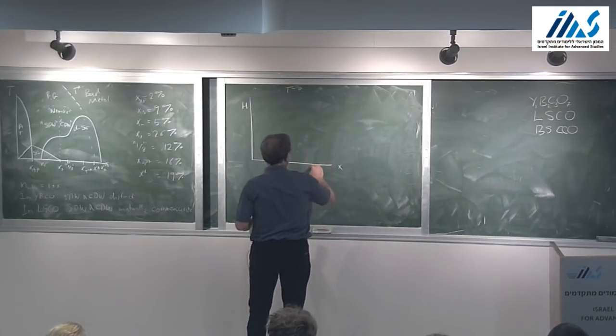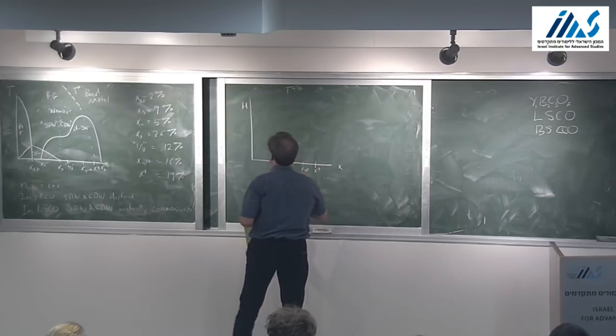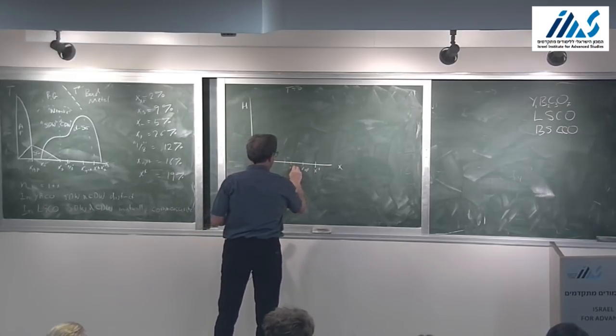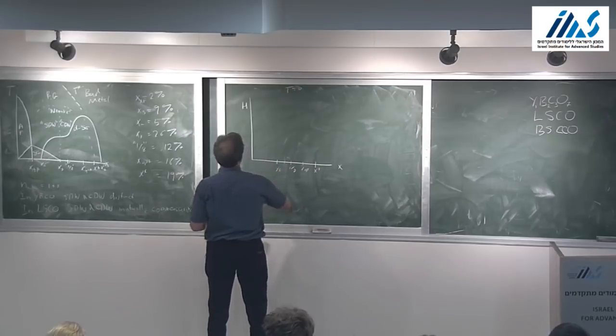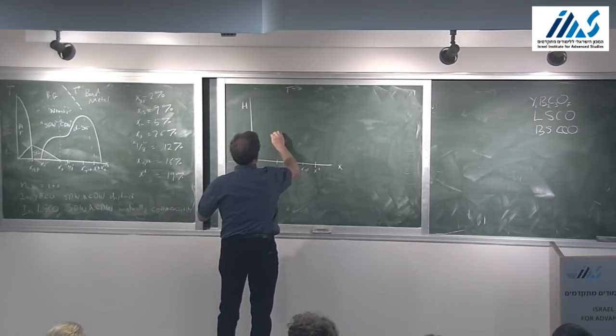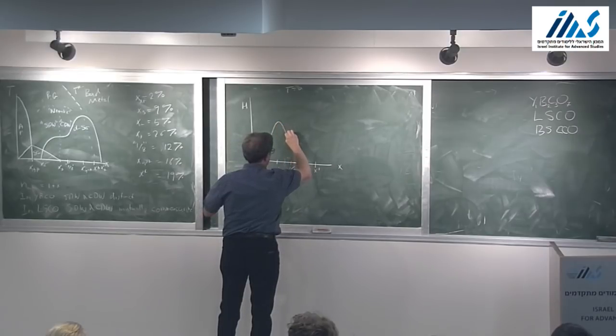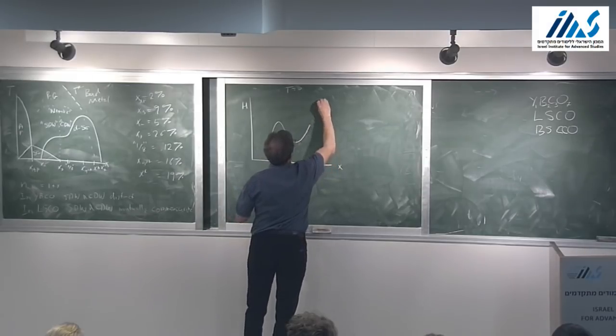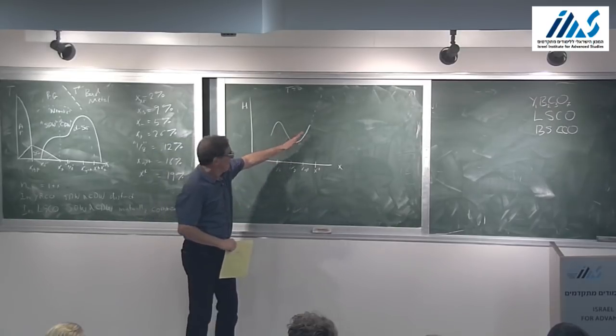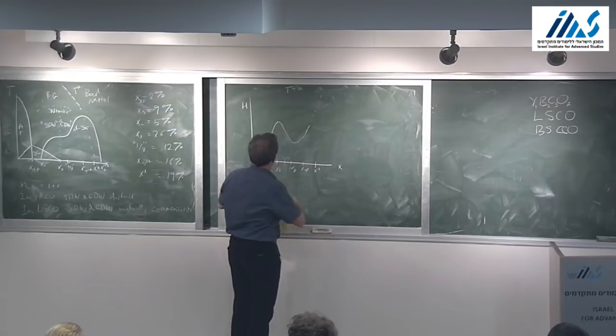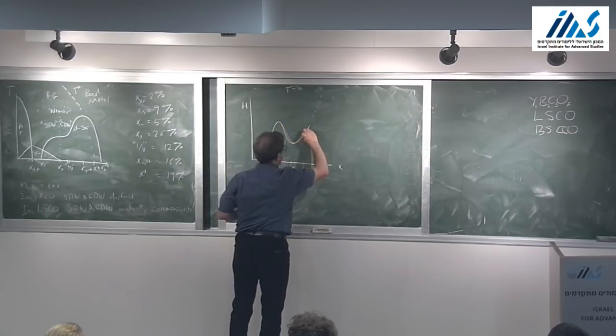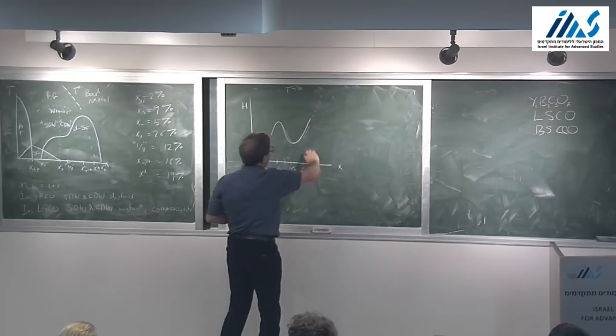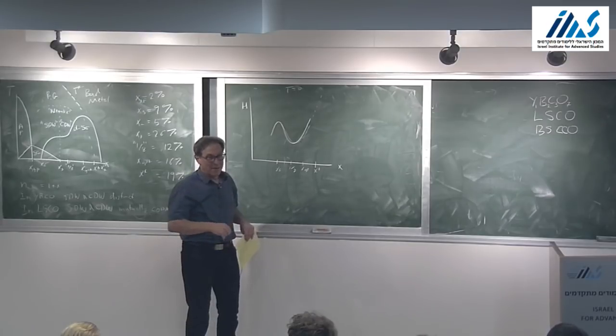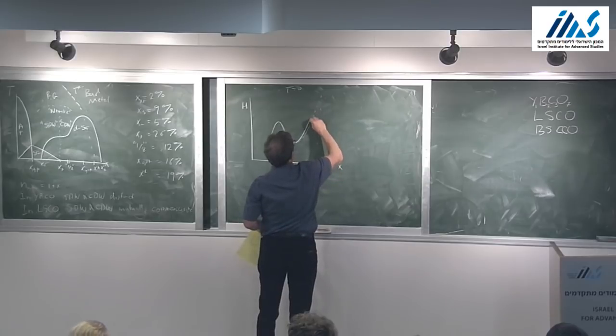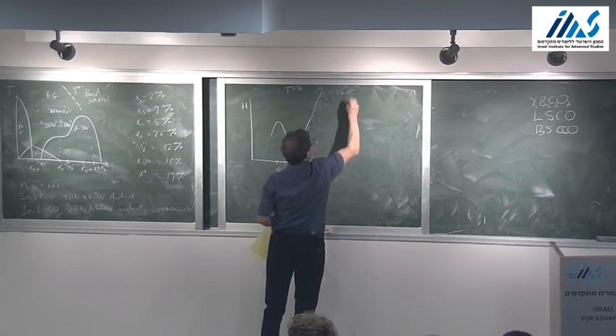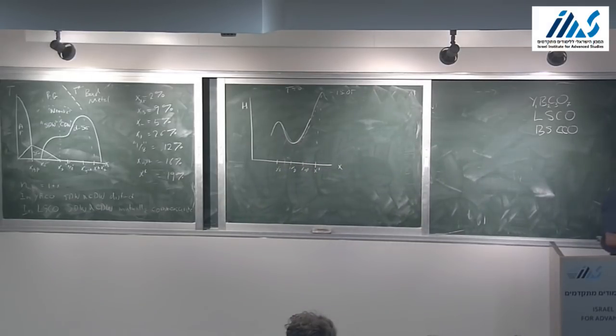Well, okay, let's see. Here's X star. Here's X optimal. Here's 1/8. Here's XS. And so HC2 has been mapped out. So it actually, I don't have my, this isn't quite right. They have it more or less to optimal doping, but it's still shooting up by extrapolating at around X star. It probably goes up to something like 150 Tesla, maybe even more. That's not a measured number.